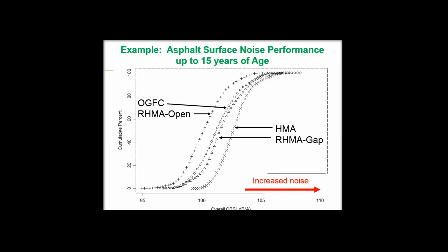This is an example of asphalt concrete tire pavement noise performance. On the x-axis, we have the onboard sound intensity in decibels, which is the noise increasing to the right. And this is looking at the performance of about 60 surfaces over 15 years. We can see that the dense graded asphalt will have a higher noise, but we can reduce that noise quite a bit by going to open graded friction courses. We get some improvement even from gap graded rubberized mixes. And in this study, the best performer was rubberized open graded mixes, which maintain their durability and keep that noise benefit for quite a while. This is an example of the type of thing that can be evaluated.